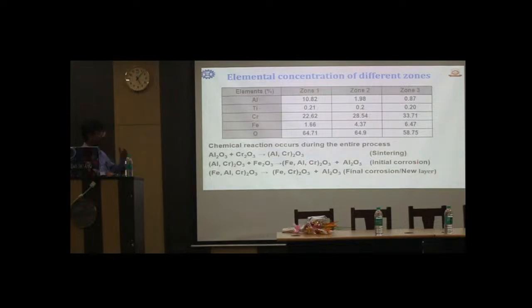And then the initial corrosion, you have this aluminum AlCr2O3, and in the presence of this Fe2O3, the iron enters into the structure, and ultimately an FeAlCr2O3 type of structure can form. So this iron can replace some of the aluminum, and then free alumina ultimately dissolves in the glassy phase. And ultimately at the final stage, instead of this iron, aluminum, chromium solid solution, it forms an iron, chromium solid solution. So with this final corrosion, the new layer is formed.